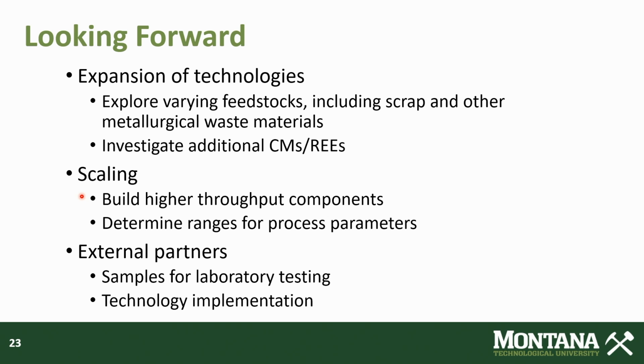Scaling, I may have mentioned it. We're planning to convert that thermocraft rotary calciner into a thermocraft auger reactor. That'll enable us to operate on a continuous basis. So we're going to go from gram quantities to kilogram quantities of product, showing that it can be effectively scaled, and also determine the optimal ranges for the various process parameters. You want a very robust process. So if there's operational upsets, you can recover quickly without loss of efficiency.